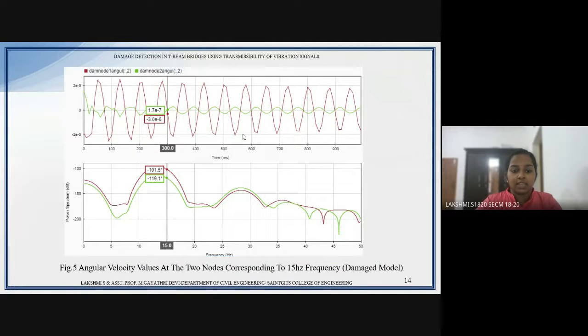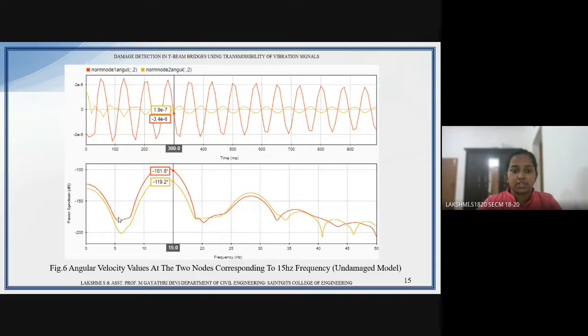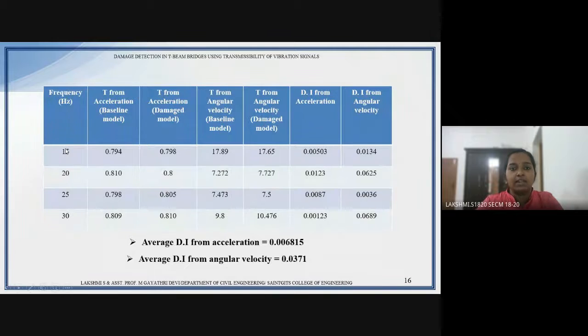These are the angular velocity results so obtained, and in case of these angular velocity results also, the coherence was maximum at 15 Hertz, as shown in these two figures. The first one is for the damaged model, and this figure is for the undamaged model. So based on the obtained results we were able to come to a conclusion that maximum coherence between the two signals from the two selected nodes was in the frequency range of 15 to 30 Hertz.